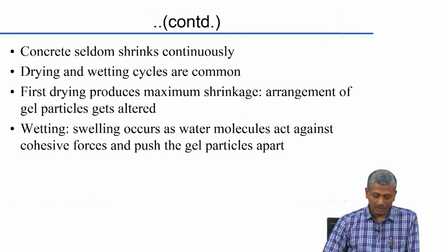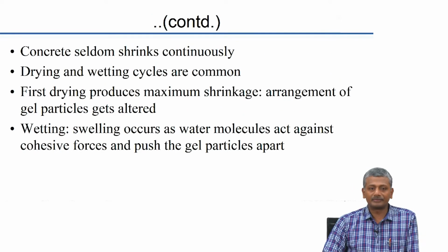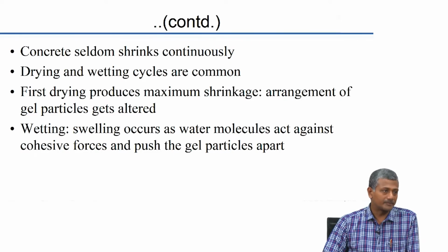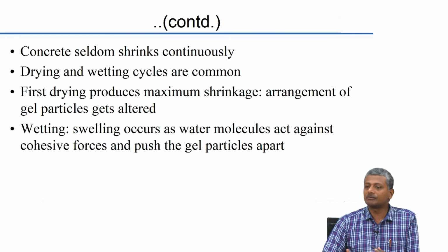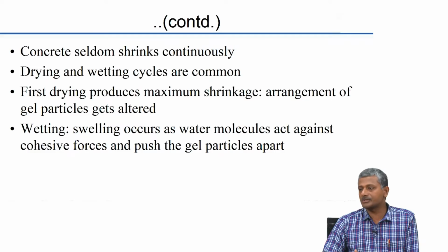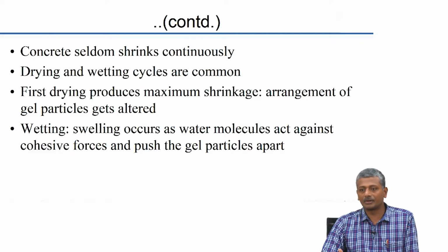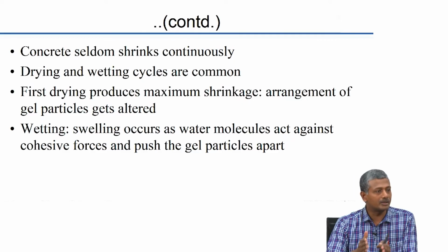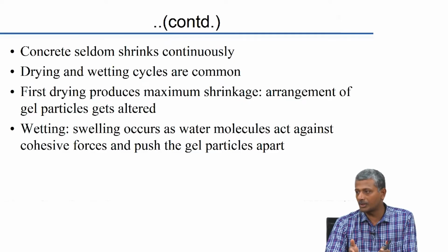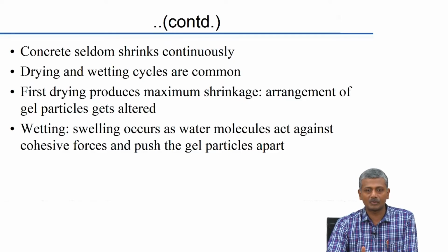Of course, one thing you need to understand is in practice concrete does not shrink continuously because there are cycles of drying and wetting. So, what we need to understand is how this cycle of drying and wetting changes the concrete microstructure in such a way that overall shrinkage or swelling actually happens in the system. Okay. In a laboratory study we saw the kind of protocol that is usually followed. You have concrete that is prepared and stored in an ideal condition like a wet curing or a moist curing for 7 days or 28 days as the case may be, and then subjected to a drying environment.